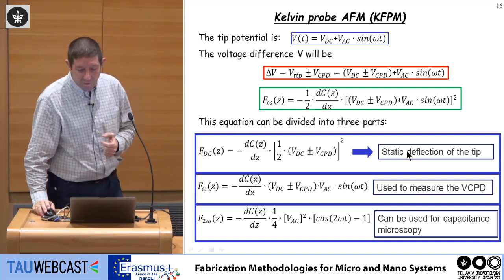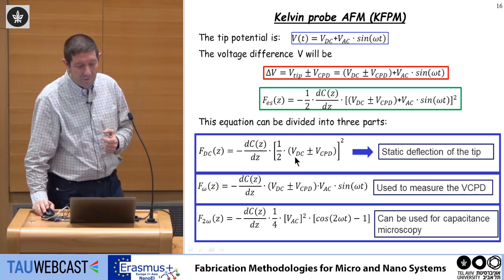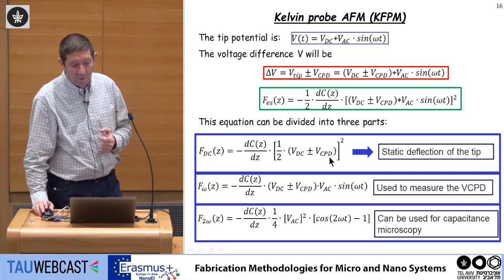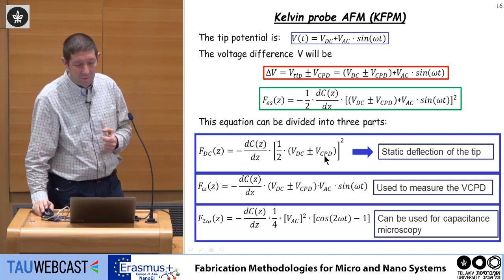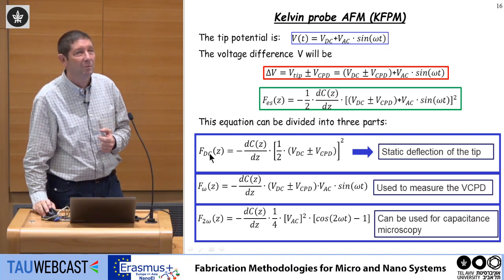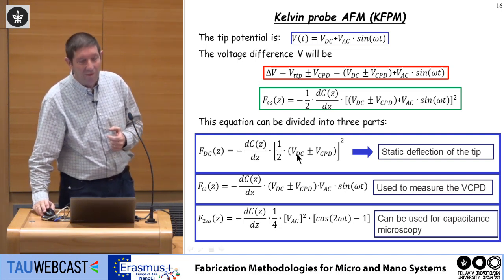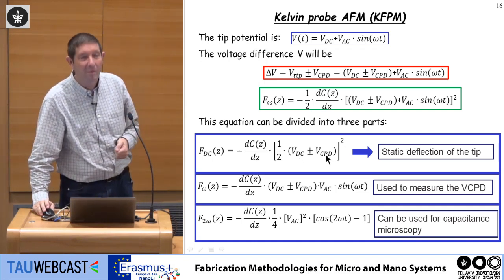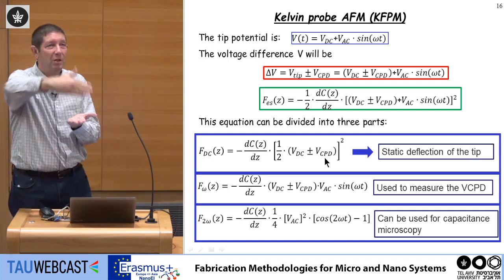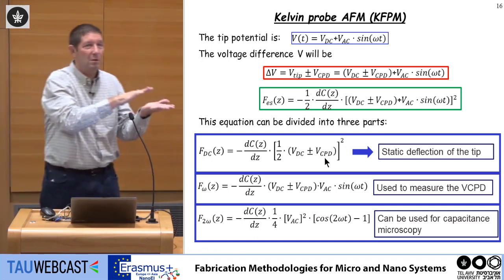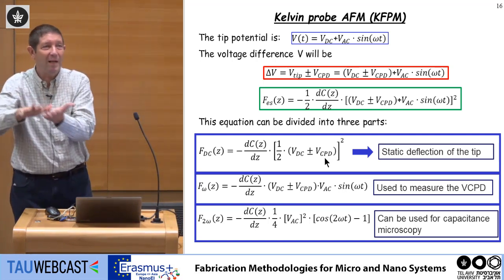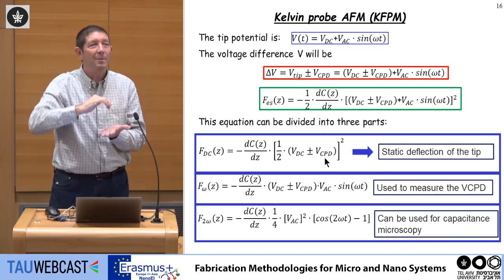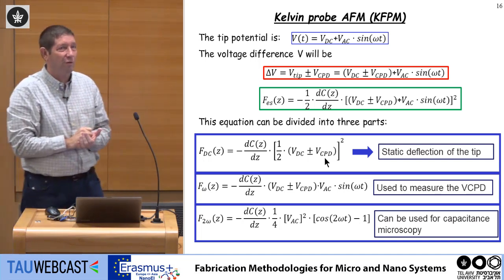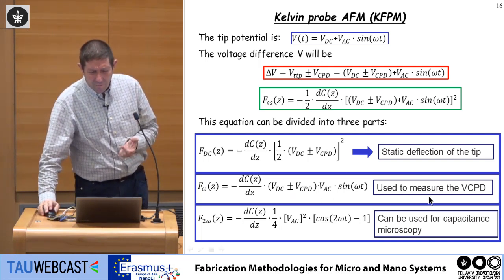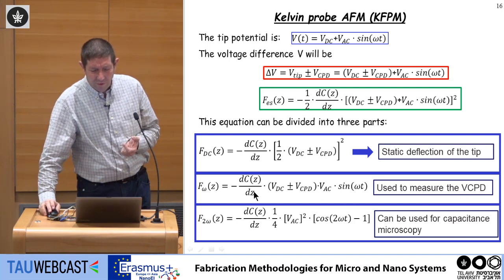This first one is a static deflection of the tip. Since I know VDC, I can calculate VCPD, because when VDC minus VCPD equals 0, this force is equal to 0. When the force is equal to 0, the VDC for that specific force gives me the potential difference. So I can actually map the potential difference of my wafer. If I have silicon, next to it silicon dioxide, next to it a piece of dust, I can see, not mapping the topography, but mapping the potential of the surface. The second component can also be used to measure VCPD, because when this force is equal to 0, this component is also equal to 0.